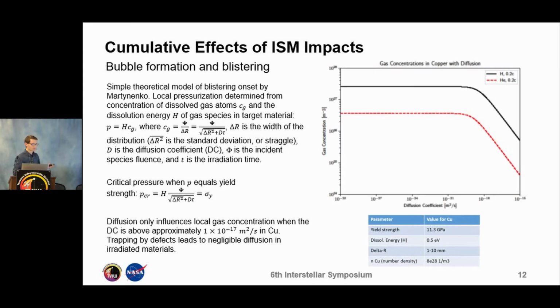A simple theoretical model of blistering onset was produced by Martinenko back in 1977. The local pressurization is determined from the concentration of dissolved gas atoms, C sub G, and the dissolution energy of the gas species in the target material.